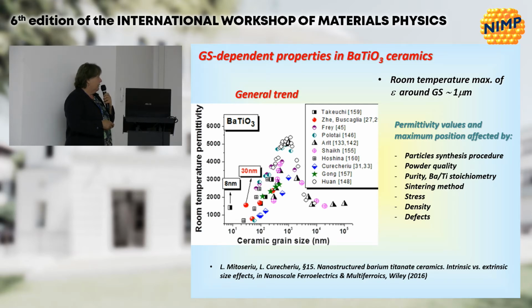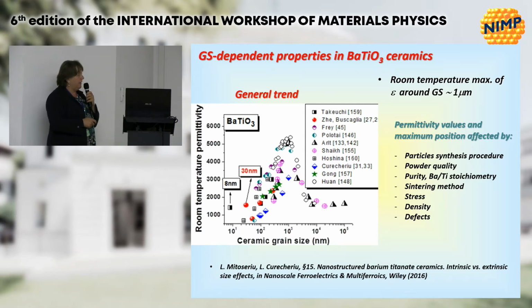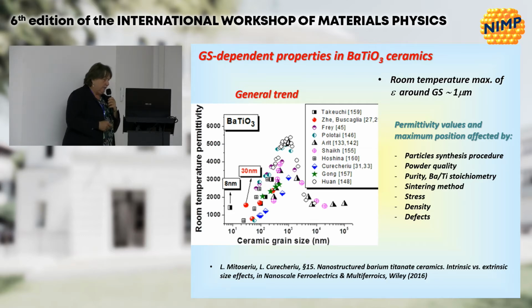And for a given grain size, there is a variability of up to about 1,000, 2,000 maybe, difference between permittivities, which was explained at that time, let's say maybe 10 years ago, as coming from the purity of grain boundaries. If the grain boundaries are clean and free of defects, people considered that they would obtain higher permittivity. If there are plenty of defects, the permittivity would be low.